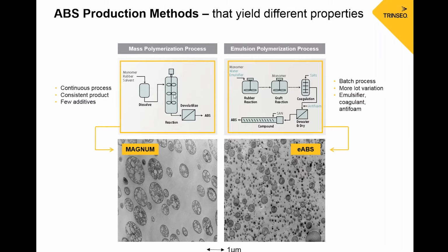This image here is depicting one reactor, but it actually goes through a series of reactors, and we're building that molecular weight of the SAN and simultaneously dispersing the rubber to optimize the particle size of the rubber through agitation. And that polymerization is started with an initiator, and in the presence of that initiator is how that molecular weight is built. And it's a free radical polymerization method. And towards the end of that, we devolatilize the unused monomers, and that goes into a recycle stream that can be reused in the process.